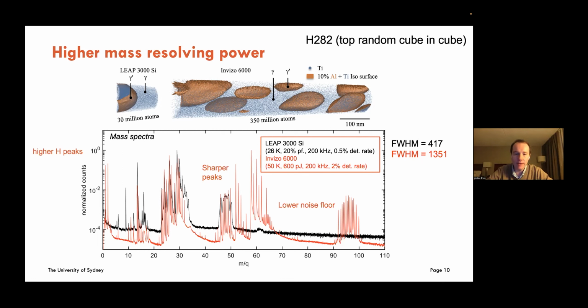And in general I'm seeing sharper peaks, and I'm also seeing lower noise floors, similar to what Levi was showing. But I am also observing higher hydrogen signal, hydrogen peaks, the 1 and 2 Dalton. So we're still investigating why that might be the case, and if we can mitigate that, because obviously Julie Canny's group is particularly interested in looking at hydrogen in metals, and we want to try and avoid all that hydrogen background.